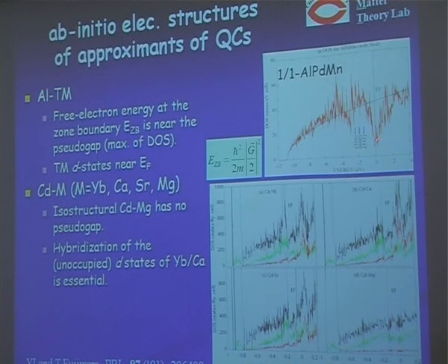But anyway, it is very close to the pseudo gap. So it seems reasonable to assume that the scattering by these wave vectors is responsible for the gap formation. But we should note that we have a transition metal d state near the Fermi level that has a very huge component which cannot be shown here. So we should check more carefully the effect of the transition metal d states.